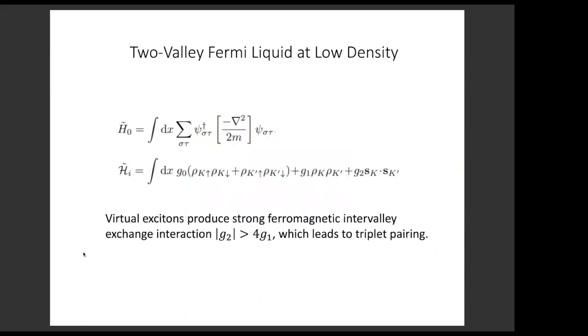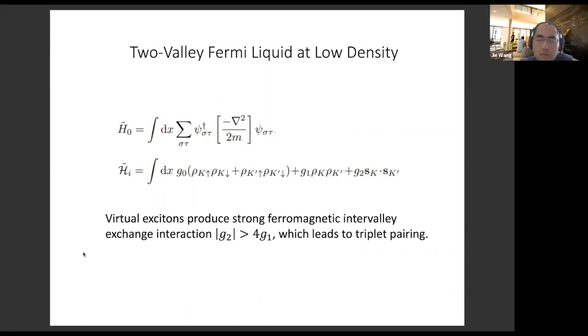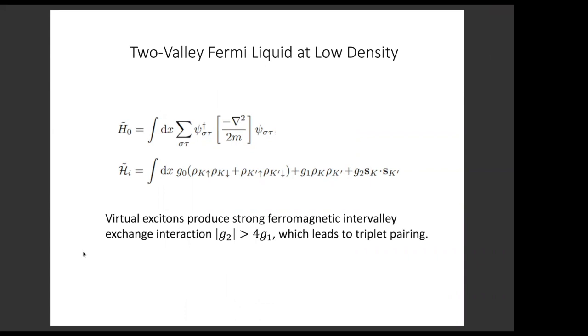Once again, at low density, we get a two-valley Fermi liquid. But now, because we have spin degrees of freedom, the interaction is more interesting. There's a repulsion within each valley. There's a density repulsion between the two valleys, G1, and there's a spin exchange interaction between the two valleys, G2. These interband processes produce sufficiently strong ferromagnetic exchange interaction, and that leads to the triplet pairing. G2 turns out to be greater than 4 times G1, and that's why we can get a triplet pairing. Next slide.